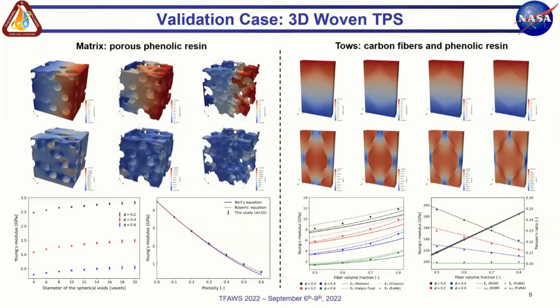Here we can observe the results of the simulations. The images on top correspond to the displacement imposed in one direction, and the images on the bottom are the stress field as a result of this displacement for the porous matrix on the left and for the tows on the right. The two plots on the left represent the Young's modulus of the matrix as a function of porosity and the diameter of the spherical pores in voxels, and how it compares with the analytical equations used for validation. And we can observe that there is a great agreement with Roberts' equation, and Bert's equation is not that far off.